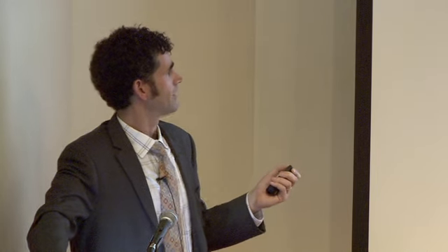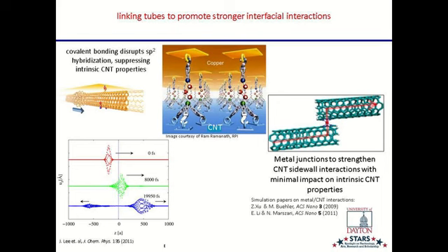So I'm not the first one to understand all this. People understood that there were problems making contact between carbon nanotubes and other materials. And the approach that so many people took was covalent functionalization, where you strongly bind molecules to the carbon nanotube surface, and those molecules will react well with a polymer matrix or a metal or whatever. You can really tailor. We're good at this. We're good at selecting these molecules, making them attach to something like a carbon nanotube, and making that interface really great at conducting. The trouble is that when you attach these molecules covalently, you do kind of the same thing.